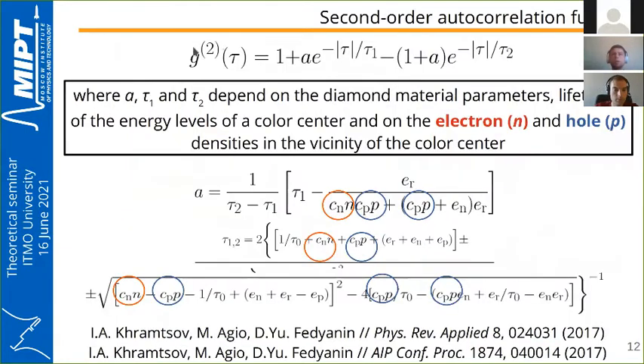So yes, I have received this expression for the G2 function, which looks similar to the optically pumped three-level system, because it has also the exponential term responsible for the bunching, and it has also the exponential term responsible for the anti-bunching. And these parameters A, tau1, tau2 depend on the diamond material parameters, lifetimes of the energy levels of the color center, like in the case of the optically pumped three-level system.